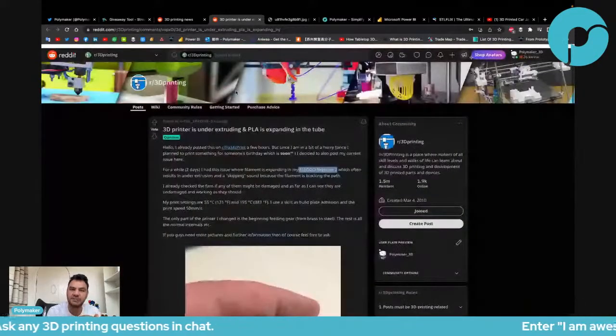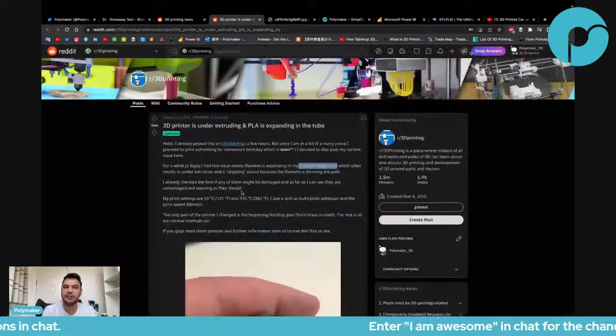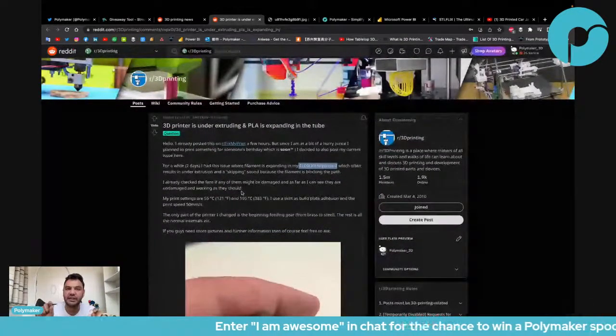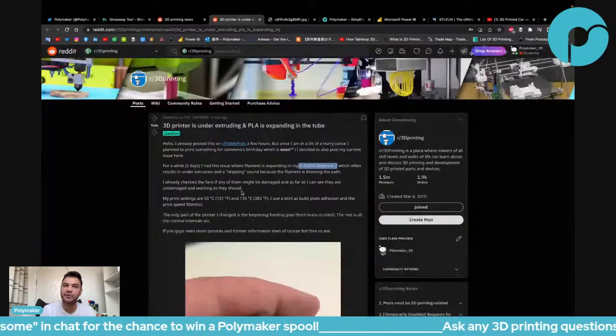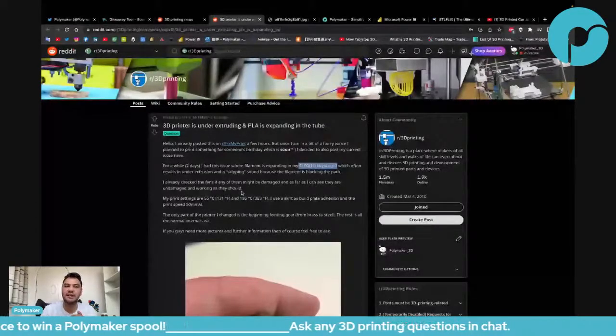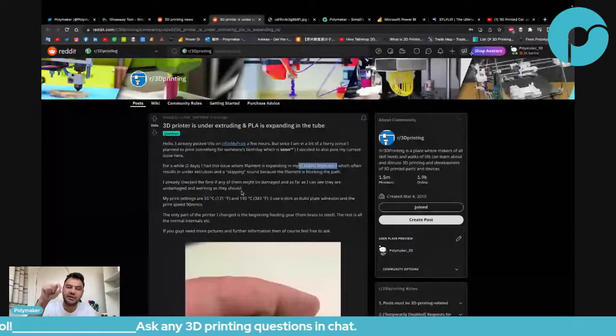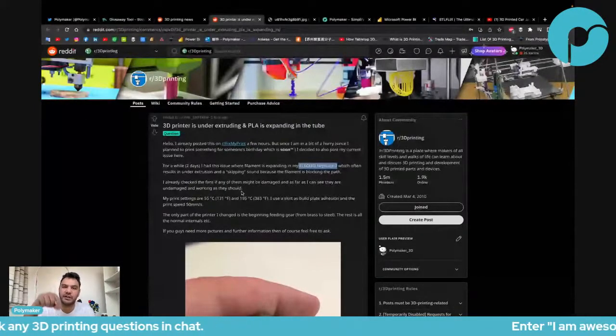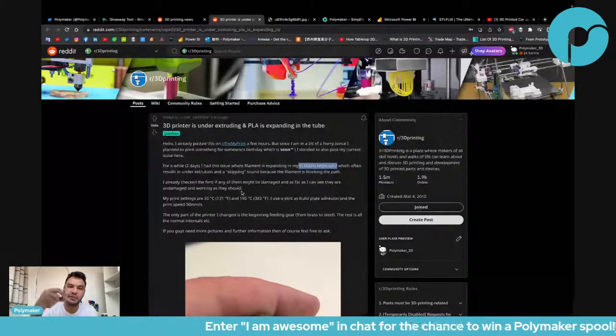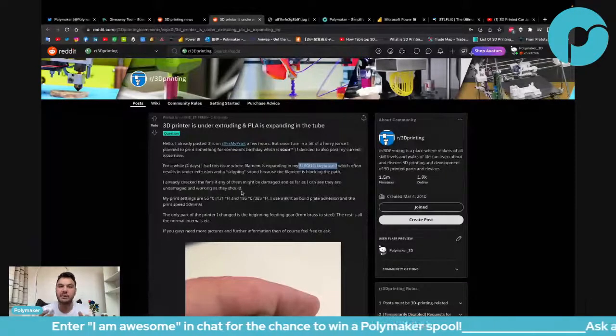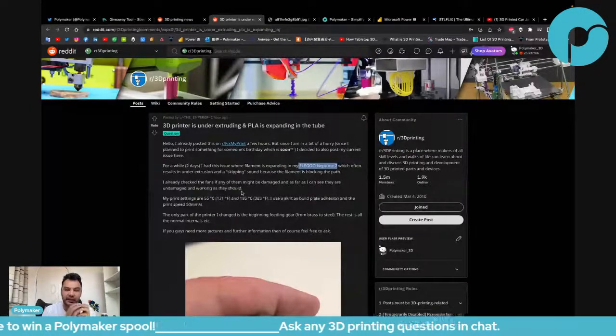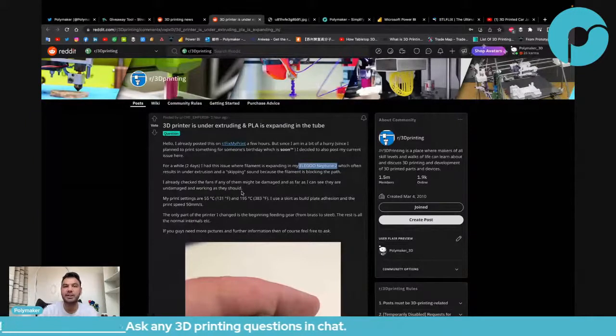crystallizing our PLA filament in order to have more heat resistance. So the heat resistance of the filament itself is 140 degrees C. But after you print it, it becomes amorphous again, so the heat resistance is 60 degrees C. But the fact that the filament itself has a heat resistance of 140 means it's much more stable in the hot end. Rather than the other PLA, where the heat resistance is 60 degrees, which means when you're printing, there is more chance to jam, because if the cold end reaches 60 degrees, then it will start to soften, expand, and then jam your nozzle, jam your hot end.